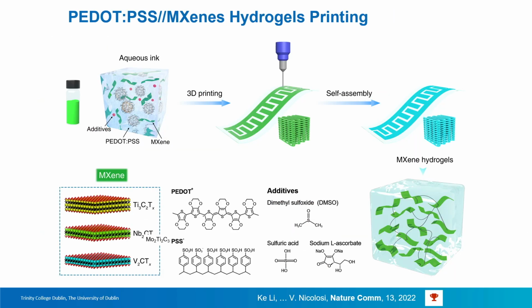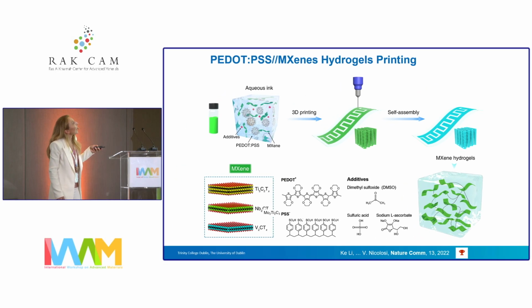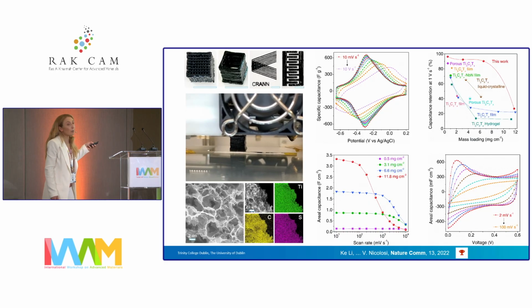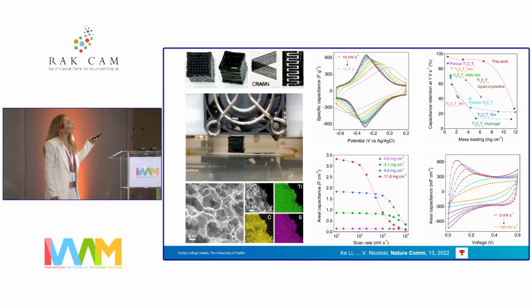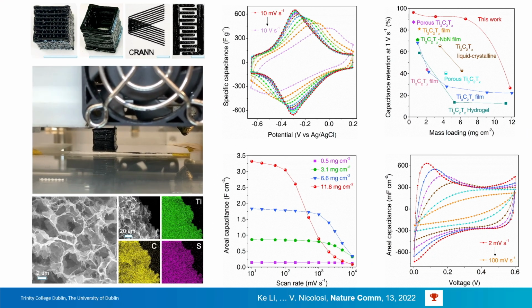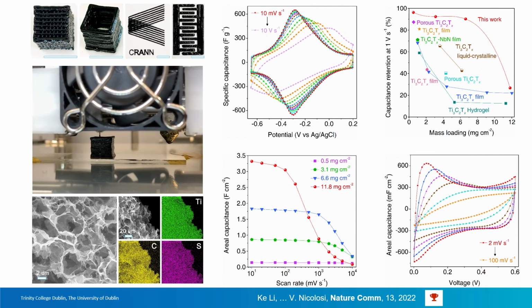Another example of the freedom in application space that we have is mixing MXene inks with PEDOT:PSS, for example, adding some additives such as dimethyl sulfoxide and sodium ascorbate to stabilize the material, and we make hydrogels. Hydrogels that are fully printable, and which again we use very successfully as supercapacitors. So again, this is a nice plot where we show the retention of the capacitance as a function of mass loading, and this is the type of performance of these devices.